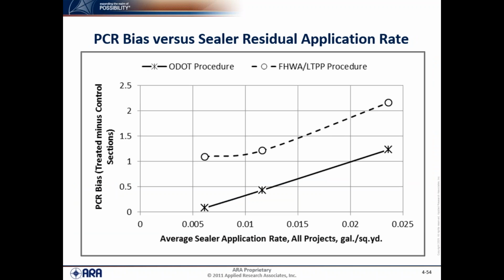Now this shows the PCR bias of the treated minus the control sections. So we're taking the PCR of the treated, subtracting the PCR of the control sections. And this shows, as a function, on the x-axis the average residual sealer application rate, and then the average bias between the treated and control. And you can see that on the average, the greater the application rate, the bigger the bias.